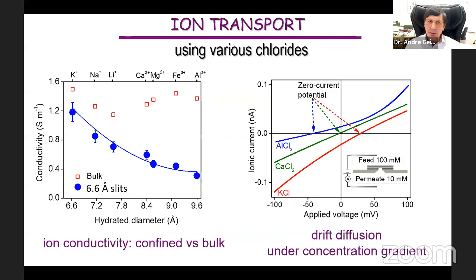We can also characterize conductivity of our capillaries by using different chloride solutions. It's all chloride solutions, but different cations here. And depending on their diameter, we see that the larger the diameter, the smaller the conductivity is. This is the bulk solution. This is our capillaries, how they behave. This is what you generally expect. Conductivity is the sum of mobilities given by anions and cations. And from this one, we can extract the sum of those mobilities.